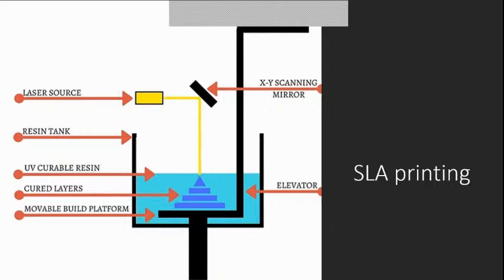So instead of moving the extruder, you use the laser source which is fixed, and you move the mirror. This mirror is moved in the XY direction to give the geometry, and based on the light falling on the resin, it prints out the geometry, or it hardens the resin at those locations, and the remaining resin is not hardened. Then the bed again goes down, or it goes up depending on the type of printer which we are using, and then the printing happens layer by layer, and the curing also happens.